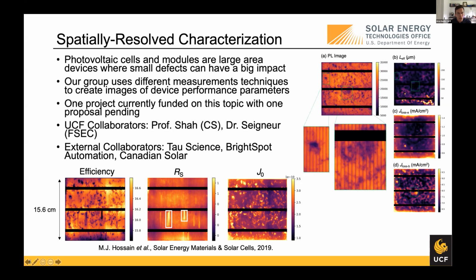So I've given some examples here of what we can do with this photoluminescence imaging, where we can create images of the efficiency of a solar cell, which is great. But more importantly, we can look at things like the series resistance. So you can look at specific defects. So you can see these bright regions have a high series resistance. That's because there's an interruption in the contact grid. And you can see that it shows up in the series resistance, and also it shows up as a dark area in the efficiency. So you can kind of quantify the penalty that these defects are causing, and also kind of figure out what the root cause of the defect is. This is kind of the first step towards that analysis. So here's something else called the J0, which is related to recombination.